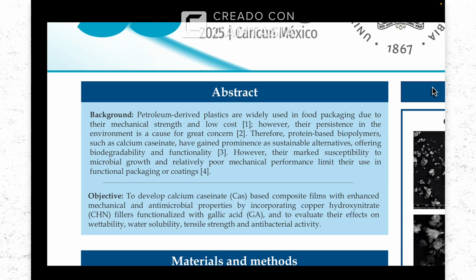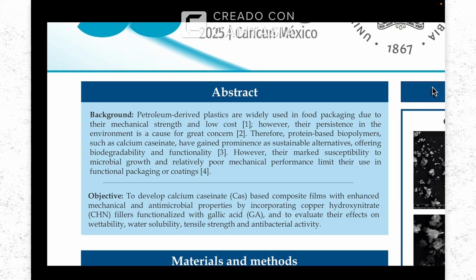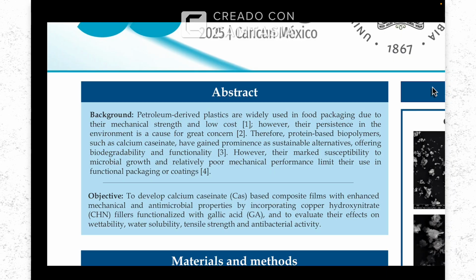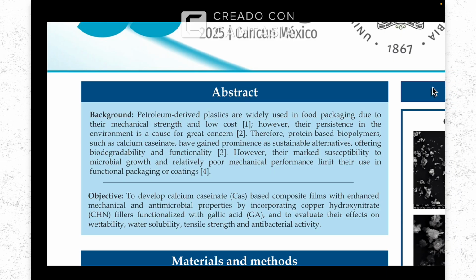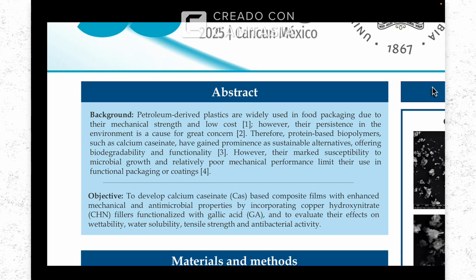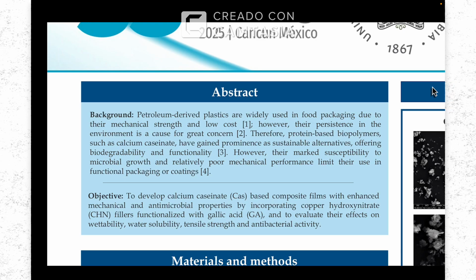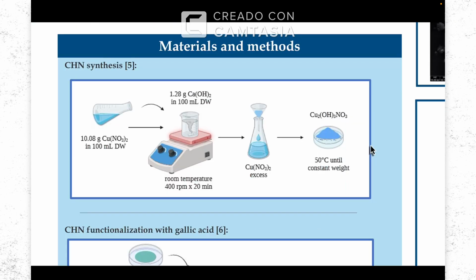Our idea was to enhance calcium caseinate film by incorporating copper hydroxynitrate functionalized with gallic acid, a polyphenol known for its antioxidant and antimicrobial activity. We prepared the copper hydroxynitrate materials by a simple precipitation method using calcium hydroxide, as you can see in the scheme.